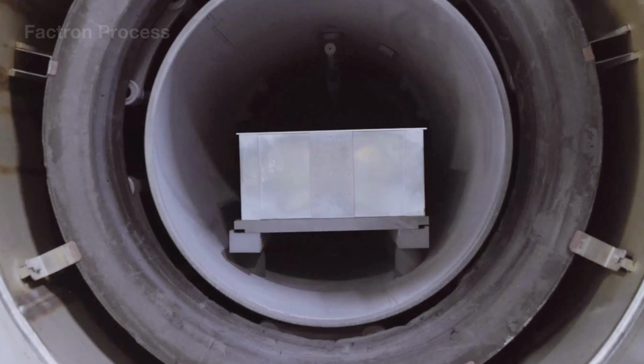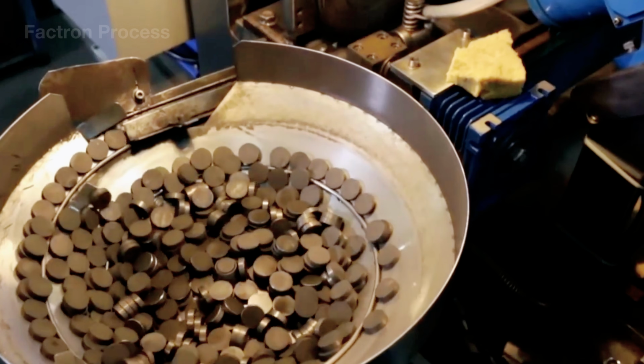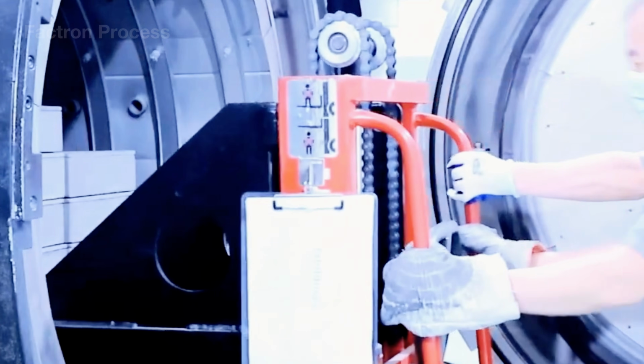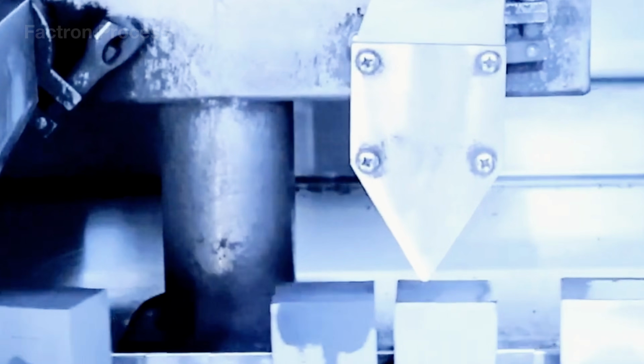The molten alloy is then poured onto a high-speed rotating copper wheel. Internal water cooling removes approximately 1000 degrees Celsius of heat in 1,000th of a second, forming flakes less than 200 micrometers thick. This limits free iron formation and distributes neodymium-rich phases more evenly before hydrogen decrepitation.